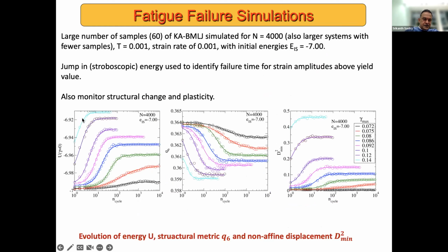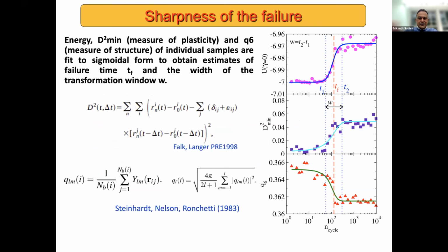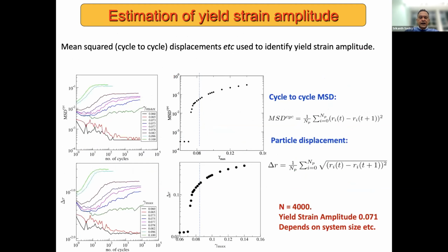So one can look at data like this, and one can ask, can I identify a failure time? And roughly speaking, the midpoint of this sigmoid-shaped curve is what I identify as my failure time. I do this using the energy, Q6, which is a measure of the structure, and it's telling you that it's becoming less ordered as the number of cycles proceed. And also D2 min, which is a measure of the amount of plasticity that you have, which is increasing as a function of the number of cycles. And so I can, for each of these quantities, compute a typical time, but also a width over which this transformation happens. Okay, this is illustrated here. I'm running out of time, so unless somebody asks me, I will skip this for the time being.